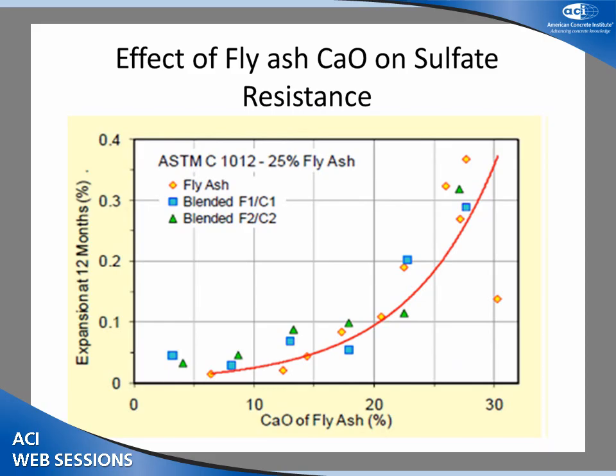Okay, now sulfate resistance is a similar graph. This is with some ashes where we blended different F's and C's, or this is Mike Thomas's data again, because I was scrambling to get some data together here. Again, related to calcium content. Typically we want 0.1% expansion or less in C1012 at a year. And when we get down below 20% calcium content in the fly ash at a 25% replacement level, we're below that expansion limit. And if you want to be sure, we just get a little more safety factor, and 15 is what we pick. So we're saying 15 to 20 may work, but you need to be more careful in the testing, and then below 15, at a reasonable level, you get good sulfate resistance.